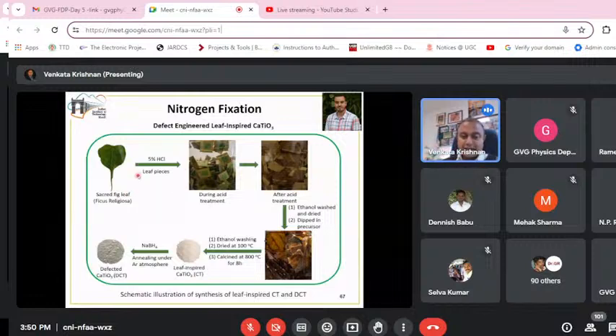So we utilized that as a sacrificial template to prepare the leaf-inspired calcium titanate, and subsequently used sodium borohydride to create certain vacancies or defects onto this calcium titanate.